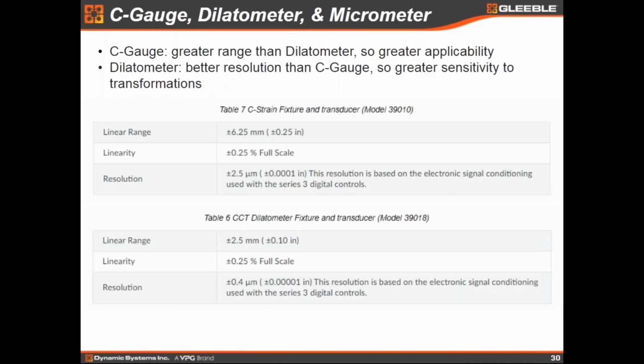Between the two gauges themselves, there's some differences. The C gauge has a significantly larger range, almost 3 times as much, but the resolution's significantly reduced, so about a factor of 5 or so. So the dilatometer has significantly better resolution if you have very subtle transformations that are very subtle volumetrically. The CCT dilatometer will be definitely a better bet. If you expect to have much more significant change, though, you may have to use the C gauge instead.